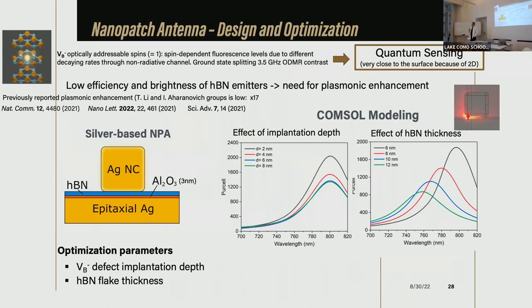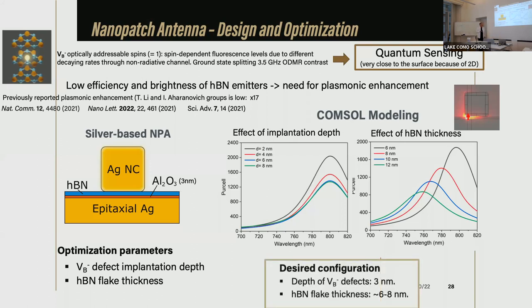But the efficiency of optical emission is low. But could we speed it up by using our nanopatch antennas? So first we did this COMSOL simulation, which helped us to answer the question, what is the optimal thickness of hBN? Is it too thin? Maybe there is quenching, not that obvious. And for a given thickness, where exactly the defect should be located. And as calculations show, the optimal condition is thickness of hBN flake.